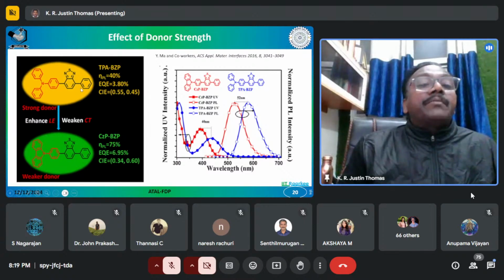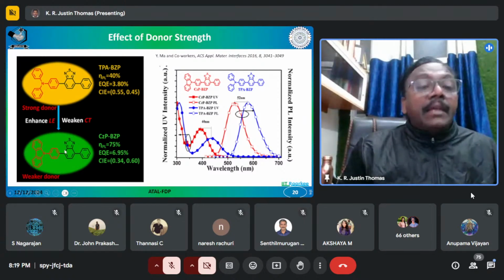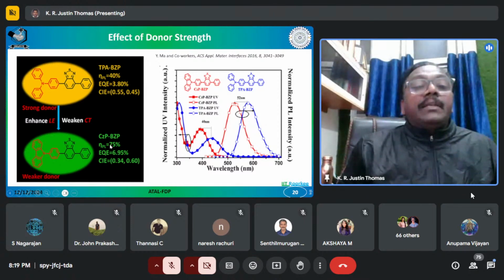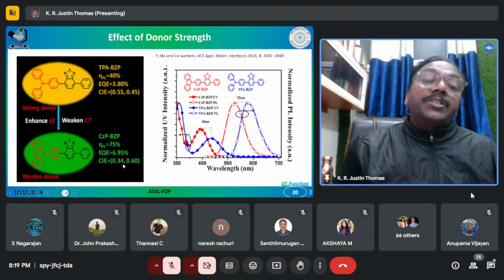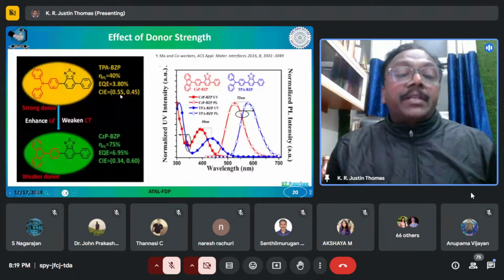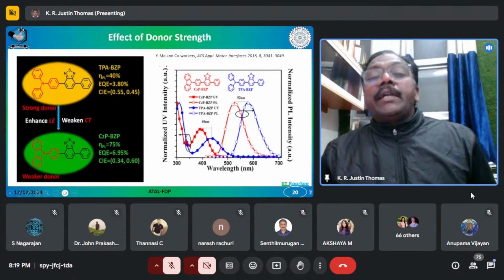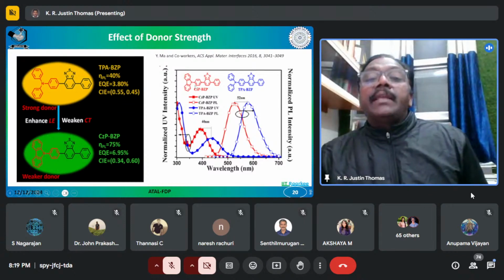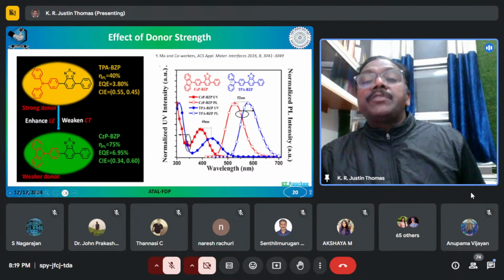If you look at the fluorescence quantum yield, because this molecule is prominently a charge transfer molecule, it shows a fluorescence quantum yield of 40%. However, this one is not prominently a charge transfer molecule, having an enhanced local excitation as well, showing a quantum yield of 75%. And in the LED, it is showing 3.8%, and this is showing 6.95%. It's a huge variation, nearly double. And if you look at the absorption and emission characteristics also, you see that the donor strength is clearly affecting them. The triphenylamine donor, which is a strong donor, leads to a red-shifted absorption and emission.